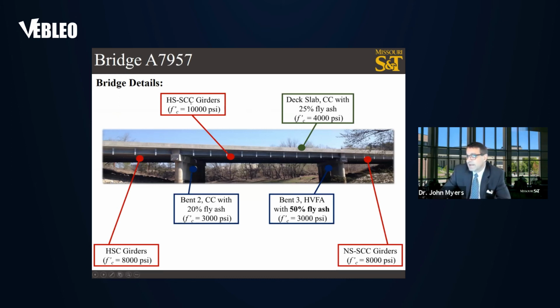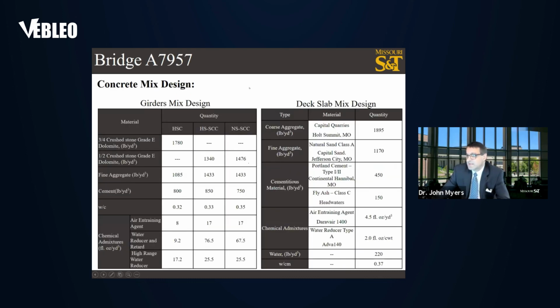High-strength self-consolidating concrete was used in girder span 2, while high-strength concrete was used in girder span 1, and normal strength SCC was used in girder span 3. The bents also incorporated high-volume fly ash concrete, the first use of it in the state of Missouri, and one of the few probably in the United States with a 50% fly ash replacement level. Here are the mix designs.